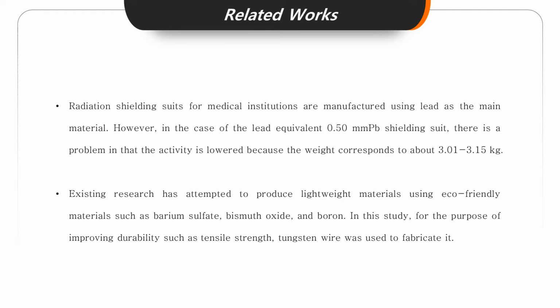Radiation shielding sheets currently used in medical institutions are manufactured based on lead sheets. However, in the case of lead shielding clothing, there is a problem in that activity is reduced due to the heavy weight. In general, apron, which corresponds to 0.5 millimeter of lead equivalent, weighs about 3 kg. Also, since apron is shielded from shoulder to knee, wearing it for a long time can put a strain on the body.